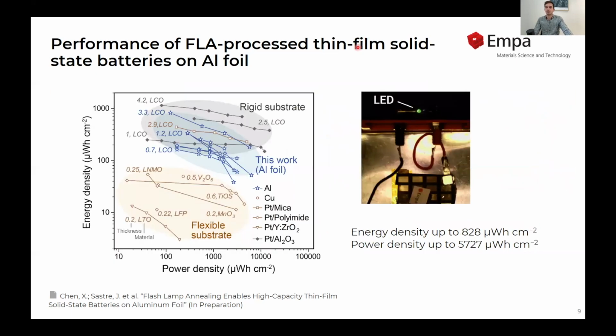Then we, of course, evaluated the performance, and compared this to standard rigid substrate thin film batteries and other devices that have been reported on flexible substrates or low-cost bendable substrates. What we observe is that with our FLA technique, with thin film batteries fabricated on aluminum foil, we can achieve performances almost the same as on rigid substrates, and orders of magnitude higher than what has been previously reported for flexible substrates. For example, on copper, or on flexible mica with a platinum current collector, or on polyimide, a polymer, etc. Only this work on mica is comparable, but of course mica is a ceramic, so it allows high temperature sintering, but it complicates the processing a lot because of the need for a very thin mica substrate.